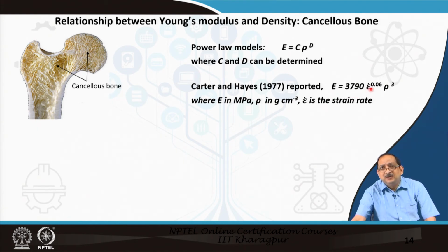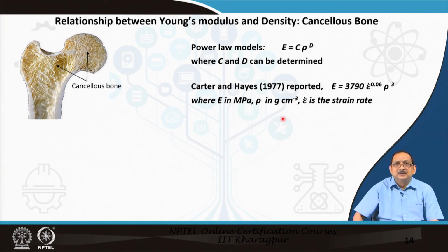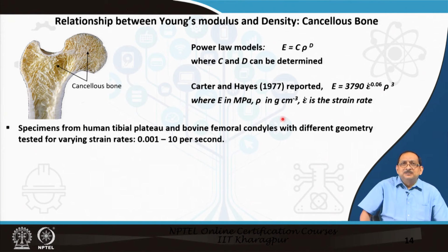The first pioneering work by Carter and Hayes in 1977 reported a very important relation: E is equal to 3790 strain rate to the power 0.06 and rho cubed, where E is in MPa, rho is in grams per centimeter cubed, and epsilon dot is the strain rate. Specimens were taken from the tibial plateau for this experiment, and also bovine bone, which is cow bone, the bovine femoral condyles of different geometry, tested with strain rates varying from 0.001 to 10 per second.